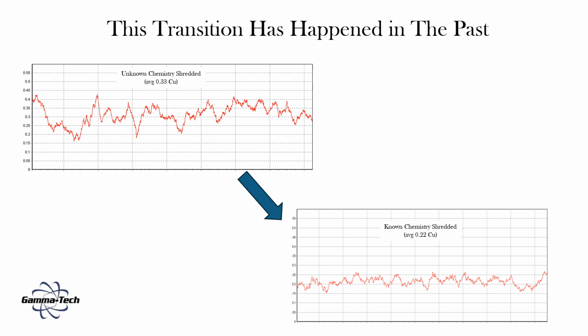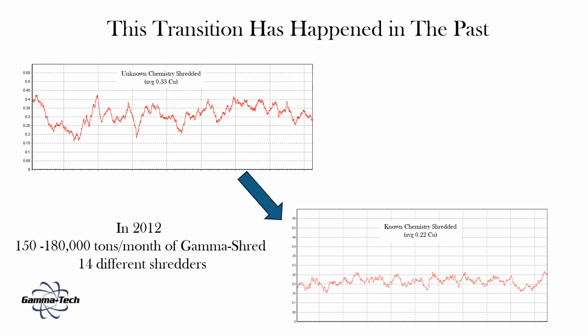And here's the important part. This is not hypothetical, theoretical, idealistic. This has happened in the past. That graph in the upper left-hand corner of the screen is the same shredder as the lower right-hand graph 6 months later that controlled the process with the exact same separation equipment, the exact same shredder mill, except able to know and report the chemistry of the scrap to their consumer base. That's happened. And in fact, in 2012, 14 shredders had analyzers and were producing a low copper, low variability, guaranteed chemistry grade of shredded, and about 150 to 180,000 tons, most of which were on the river system, were being produced by those shredders.